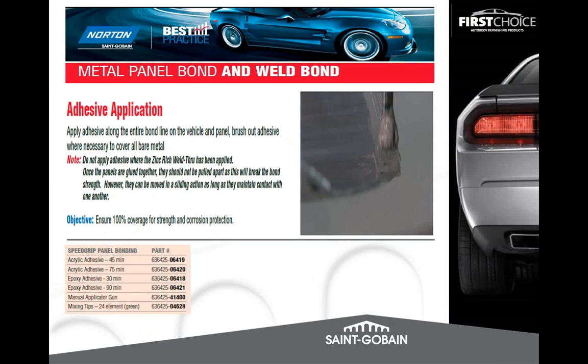Actually, I'm sorry, the epoxy can be welded only in its wet state, where the acrylic can be done throughout the process, preferably in its wet state. But the neat thing is say somebody puts a quarter panel on at night and realizes, oh, I didn't do the taillight section, or I didn't do where the new panel meets the old panel. The neat thing about acrylic is it can be resistance spot welded through at any time during the repair, where an epoxy cannot. Once it's dry, unfortunately, you have a very high probability that it's going to catch on fire.